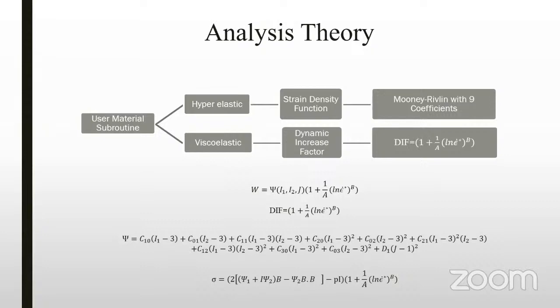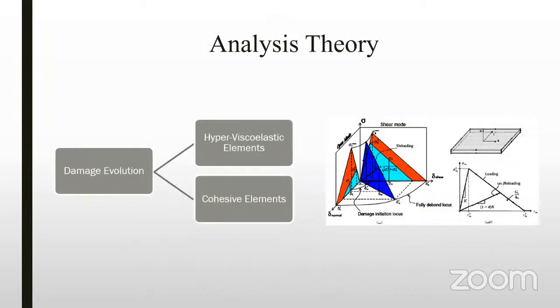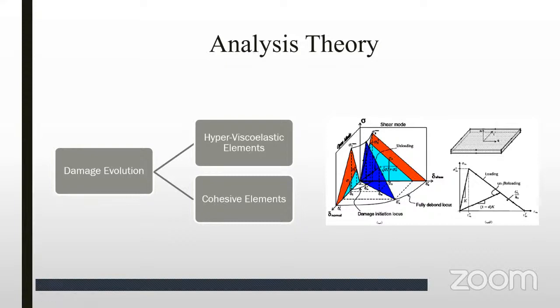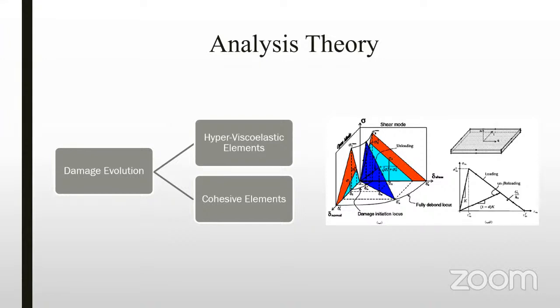As we can see, this is the Mooney-Rivlin strain energy density function with 9 coefficients. So I had to do some experimental tests to calculate these 9 coefficients of the Mooney-Rivlin model, and also to calculate A and B, the coefficients of the dynamic increase factor, which are representative of the viscoelastic behavior of the elastomer. In the following, to predict the damage evolution, I have used the hyper-viscoelastic elements based on the user material subroutine equations that I discussed in the previous slide, and the cohesive elements for the damaged area based on the bilinear traction separation constitutive model.